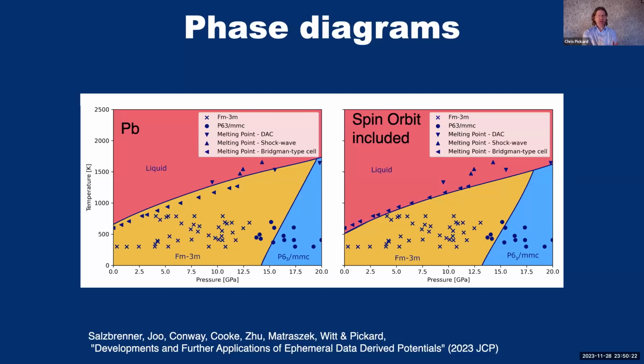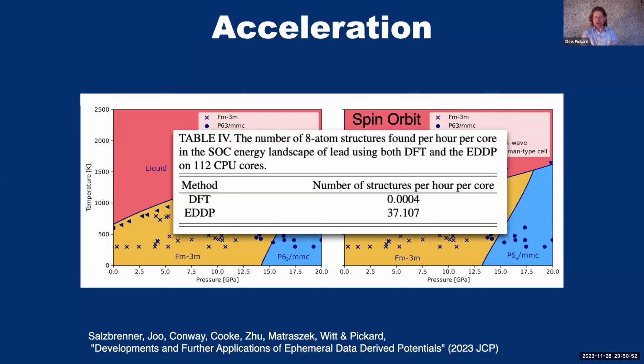And also what's incredibly striking for me is these fairly simple potentials are giving essentially quantitative agreement with what's experimentally known about the phase diagram of lead, to the point that we didn't need experiment at any point in these calculations. If we, having never seen a phase diagram of lead, presented our phase diagram of lead, it would agree reasonably well, with some variations in the pressures of the phase transition between FCC and HCP. But not only that, is how fast these calculations are.